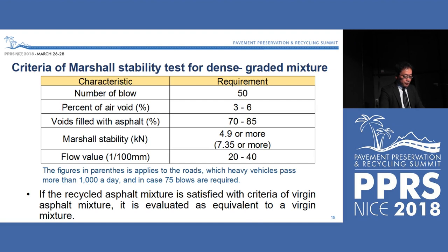This table shows criteria of the Marshall stability test for the dense graded mixture in Japan. The optimal asphalt content is determined, which is the range where all target values are satisfied. This method and criteria are the same as for testing virgin asphalt mixture. If the recycled asphalt mixture satisfies these criteria, it is evaluated as equivalent to a virgin mixture.